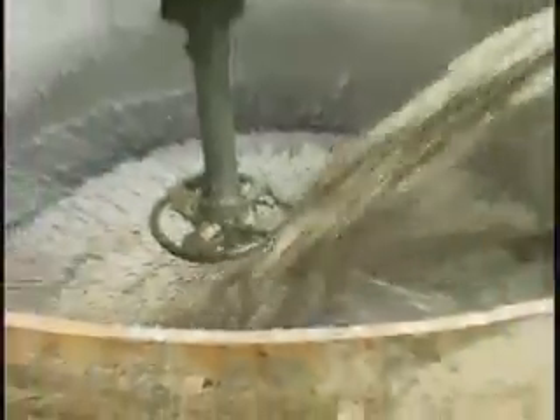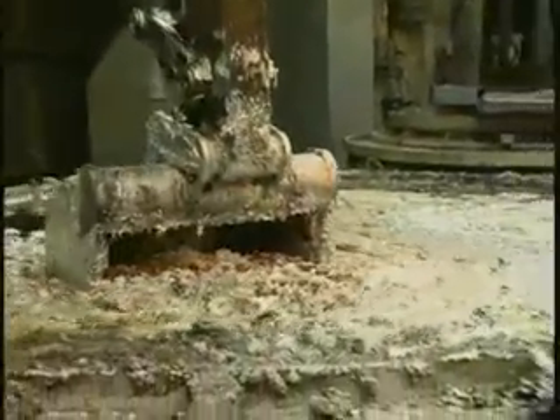As soon as, for example, the copper is removed from the lead by adding sulfurous agents, the liquid lead is pumped onto the next vessel. Here, the next refining step takes place. Applying the Parkes process, silver is removed by adding zinc. The silver-zinc mixed crystals accumulate on the surface. They are lighter than lead and therefore can be skimmed off with a shovel.